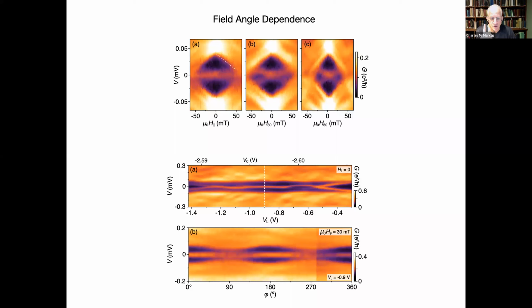Well, there are two things to point out. The first is that here, let's look at two different pieces of data. One piece of data is when you have an external magnetic field. Notice it's only 30 millitesla. So 30 millitesla swinging around, you'd say that's not really much field to be destroying superconductivity or fooling around with Majoranas or whatever. The Majoranas need a Tesla.